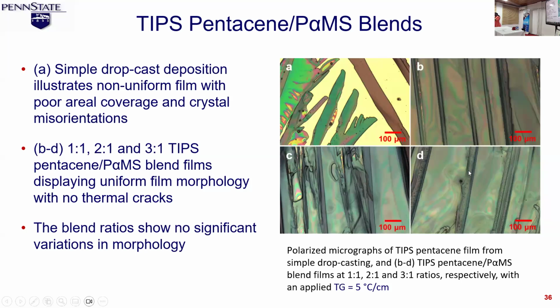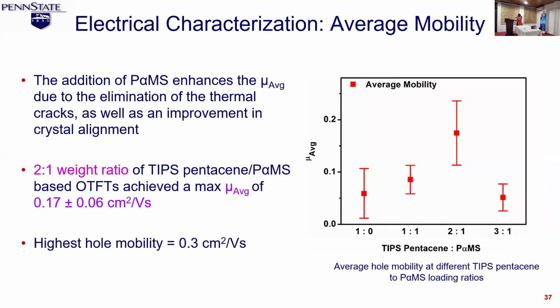And as you notice from the optical images, again, the crystal sizes were good, coverage was good, so there was no huge difference in terms of just looking at the morphology. The average mobility, however, showed a drastic difference in the devices. The 1:0 ratio is just pure pentacene. The 1:1, it will be 1 part pentacene, 1 part P alpha MS. The 2:1 showed the highest average mobility. And then the 3:1 dropped again.